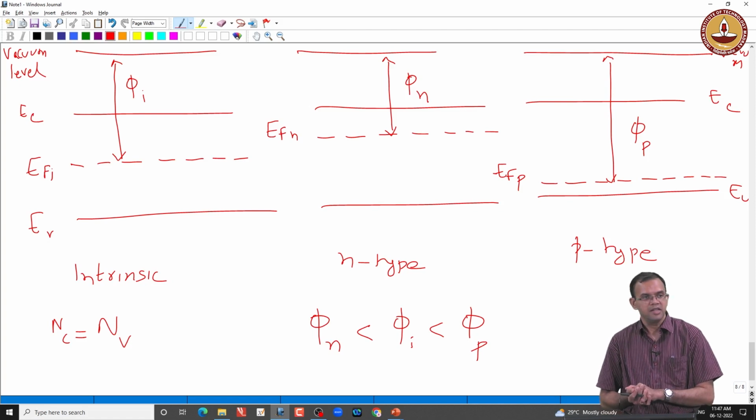Okay. Any other questions? Sir, after doping, how to ensure how much depth doping happens, like depth profiling? So one is you can control the time and temperature. You can also measure the dopant depth. There is a technique called secondary ion mass spectroscopy (SIMS). So SIMS can be used for depth profiling.